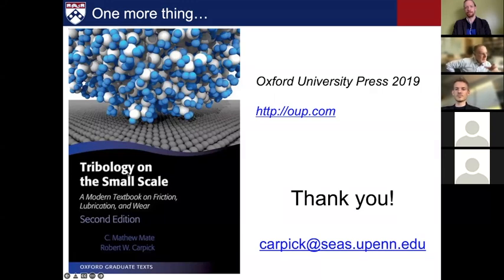But you probably think about point defects or maybe grain boundaries. Those tend to increase friction. And I believe it was Tobin Filleter's group in Toronto has looked at disordering effects. And the short answer is that, you know, disorder can lead to out of plane deformation, so roughness. It can lead to higher local energy at the defect sites. And that it would tend to increase friction. And Phil's commenting, there's some good Prandtl-Tomlinson with temperature simulations on the effect of disordering defects in graphene.